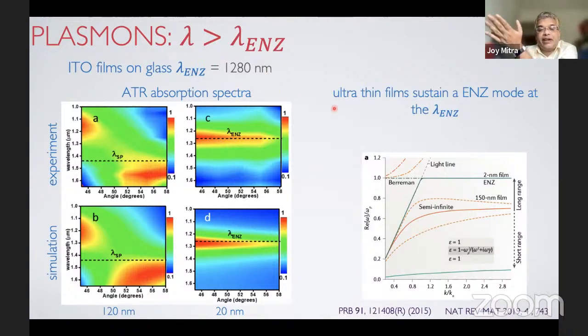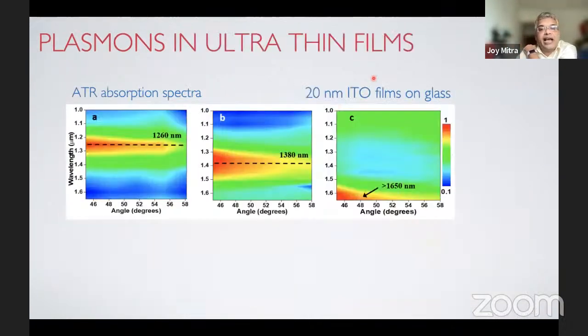So we said, okay, fine, it's very easy to check now. Let's check for the other films. And indeed, when we tuned the lambda ENZ of films from 1260 to 1380 to 1650, we saw that the plasmon mode in the thinnest of the films, the 20 nanometer films, was essentially shifting.